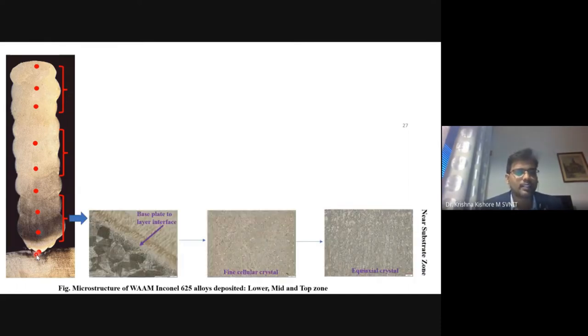So if you see at the interface, the substrate plate which we have taken is also Inconel. So the base Inconel microstructure, if you see, is like this. And once it is melted and deposited, because of the instant grabbing of the heat by the substrate plate, there is a dendritic growth in the first layer, and in the second and third layers, we can see a controlled fine cellular structure or equiaxed structures in the microstructure. That means still there is a need to achieve this at the base interface layer. In the interface layer, we are not able to achieve this fine cellular structure.